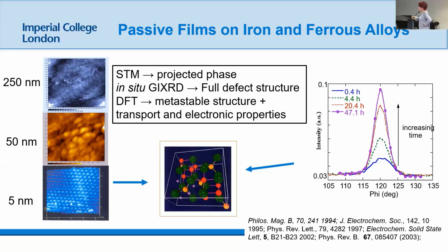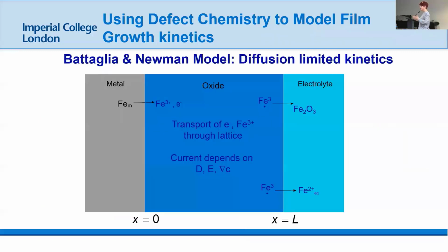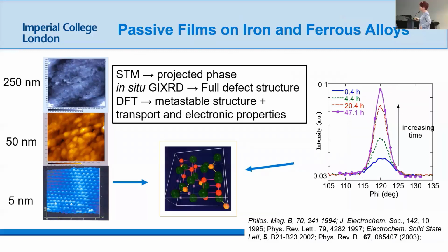So we use STM to show this, but that doesn't really give you a full structural determination. It tells you, yes, it's crystalline, but it doesn't tell you what it is. So then we did some grazing incidence X-ray diffraction in situ. And this is just a snapshot of those data. This is the 002 peak of a single crystal of pure iron, and this is the passive film growing over time. The peak width here is very broad. That's because it's nanocrystalline. But from doing this and mapping exhaustively the whole of reciprocal space, you're able to pull out a full crystallographic description of what that passive film is and how that changes with things like potential and pH. So now we have something that we can model, right?